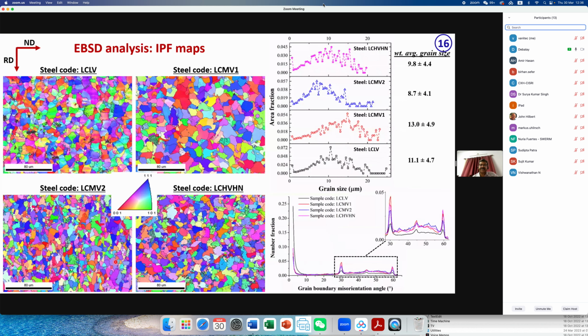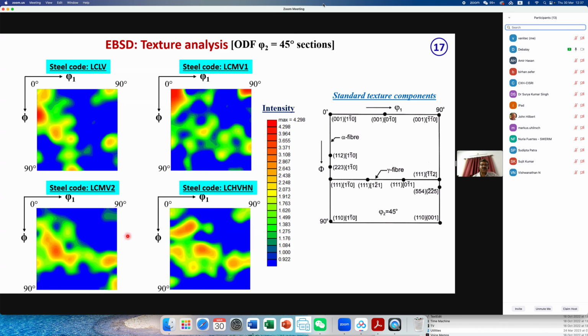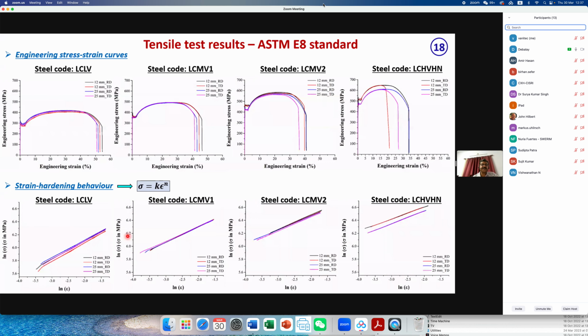We have done EBSD study. Again, you can see nice uniform grain structure and a very random kind of texture, not very strong texture. So this is expected to give good toughness property in plate steel. Not very strong. This is the ODF representation, orientation distribution function.